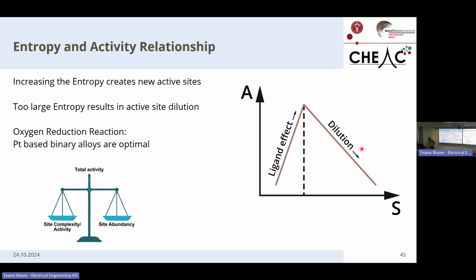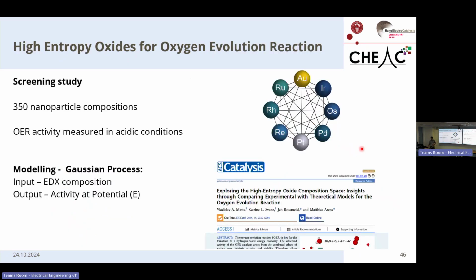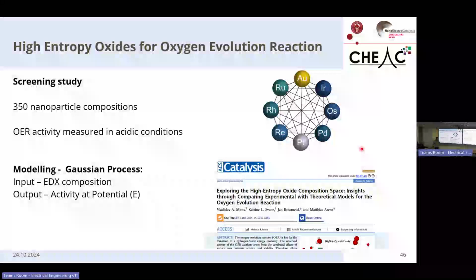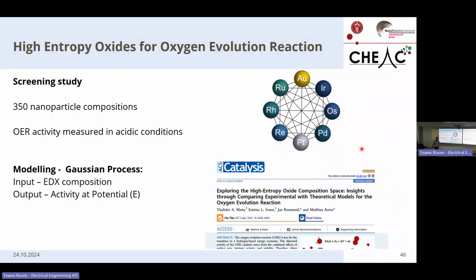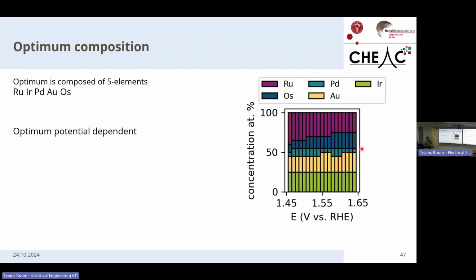But now let's take a look at what happens in case of the oxygen evolution reaction. So in the same screening study I was doing for the oxygen reduction reaction, I also measured the oxygen evolution reaction. Because, well, doing an additional measurement for 15 minutes is maybe sometimes worth it. So here we end up with the same process. We have a model that now can correlate the different compositions to the different activities, and we can predict the different optimal compositions for multiple potentials for the oxygen evolution reaction.